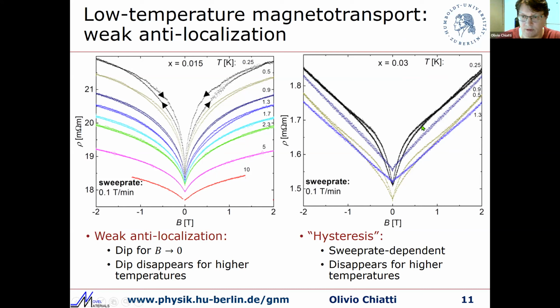The same goes for the sample with higher vanadium concentration, but the temperature where the dip disappears is lower than in the other sample. What we also observe is something that looks like a hysteresis here, which disappears at higher temperatures. And it depends on the sweep rate of the magnetic field. And it's still not clear what the origin of this hysteresis is.